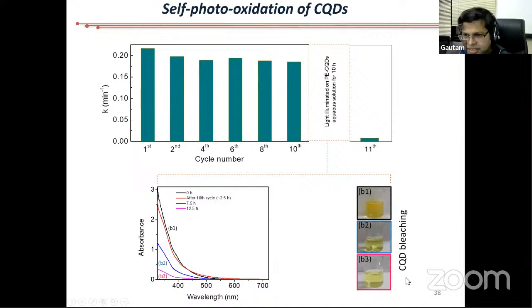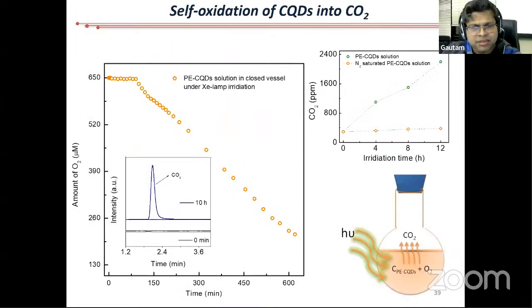You can see here these solutions B1, B2, B3. This is the carbon dot color. The carbon dot color is slowly fading. This is called CQD bleaching. This is well known. Everybody has seen that if you keep using carbon dots, their color slowly fades. We looked into why it fades, and there are many hypotheses. Certain things change in the carbon dot. What people have never seen is, when the color is changing, is there any gas evolution? When we looked into it, we figured out that actually CO2 forms.